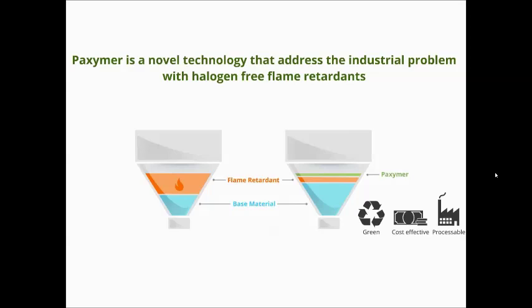And there are consequences to that. So for instance, you're going to have a tough time meeting your mechanical specifications and perhaps even your processing specs, or you have to make compromises there. What we can do is we add a little bit of our functional polymer in, which is highly compatible with the base material, and then you can reduce the flame retardant level. That is typically cost effective because the flame retardant is expensive. It typically improves the processability and the mechanical properties, and you're using less of this hazardous additive anyway, and therefore you also improve your environmental footprint, and you can move away from these brominated solutions without compromising on your product performance.